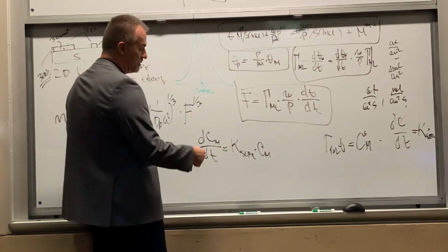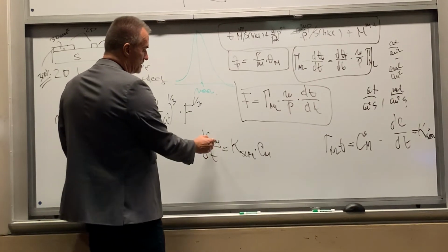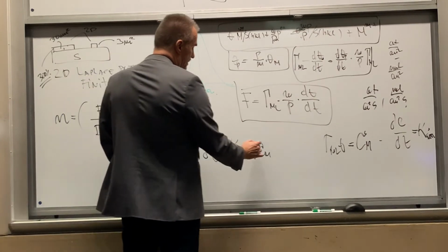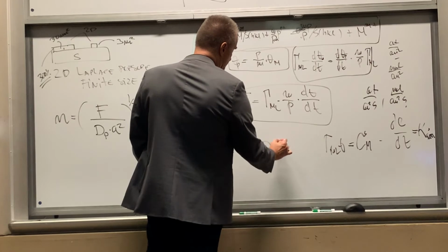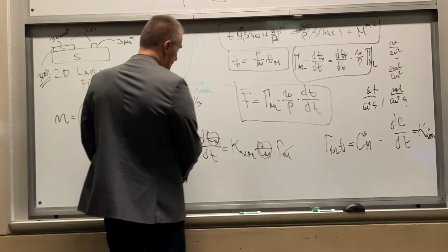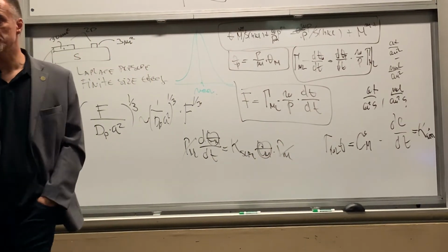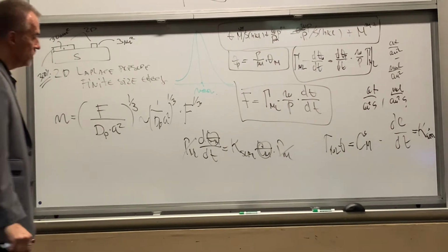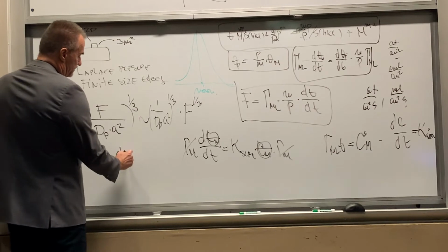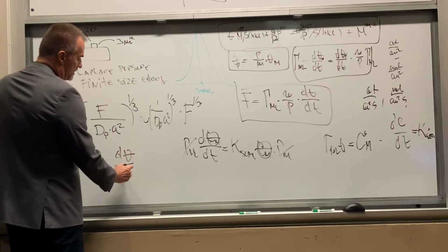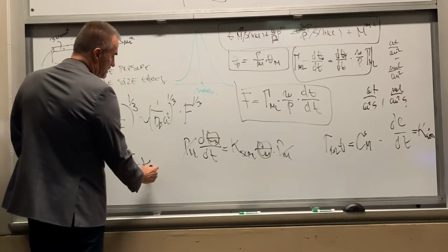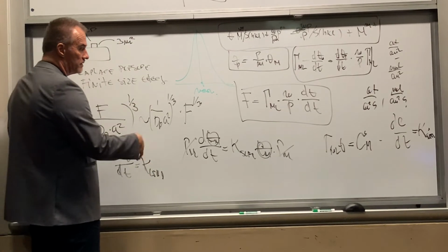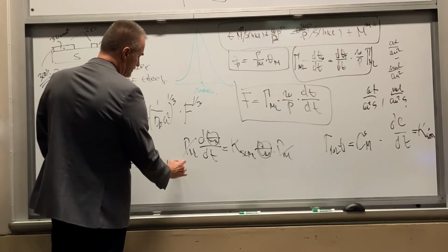Or if we get rid of the C and use gamma monolayer, and here becomes theta, then this becomes theta and gamma monolayer, right? And we can get rid of that, okay? You see that or not? So the d theta over dt, using regular chemical kinetics analogies, is the rate constant of the reaction times theta.